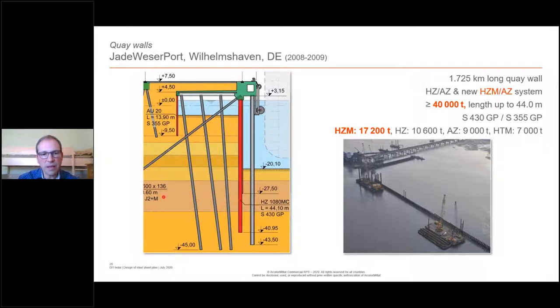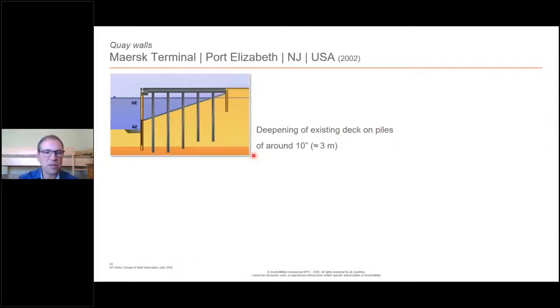And here they had up to 55 meter long piles. And also for the king piles, the HZ, they were up to 44 meters long. So 44.10, that was the maximum for a dredge level of -20. But the design level was at -23. So they increased the design level by about 3 meters to be sure that they didn't have any problems with scouring and things like this.